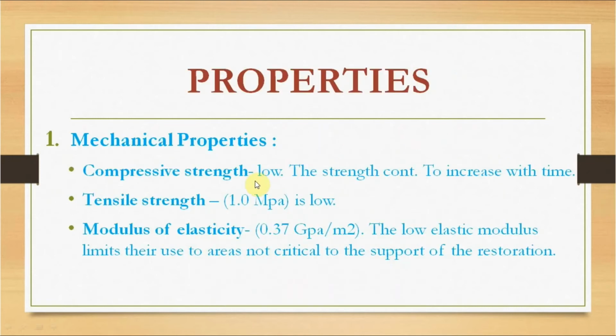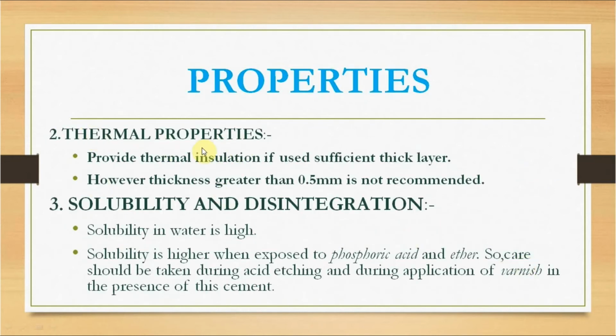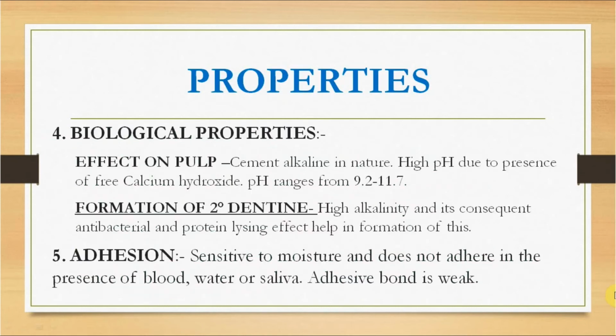Properties. Mechanical properties: compressive strength is low but it increases with time. Tensile strength is 1 megapascal. It has low elastic modulus, which limits its use to areas not critical to support of restoration. Thermal properties: a sufficiently thick layer is required for thermal insulation, but not more than 0.5 mm is recommended. Solubility is high with water, phosphoric acid and ether. Therefore, care should be taken during acid etching and during application of varnish in presence of calcium hydroxide.